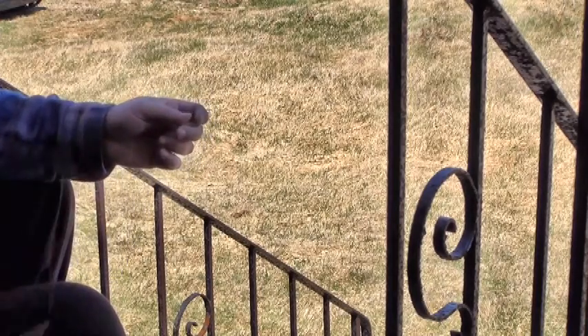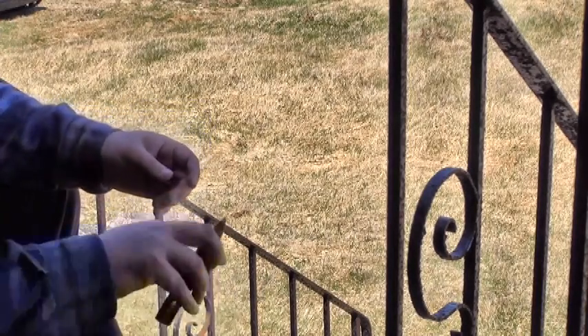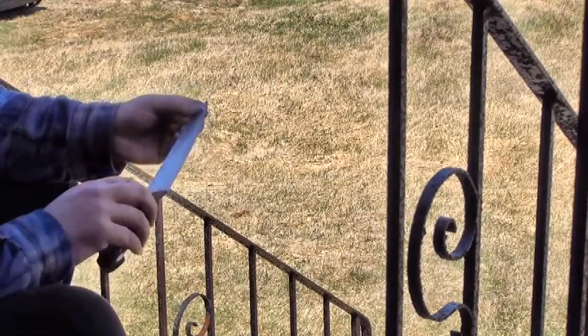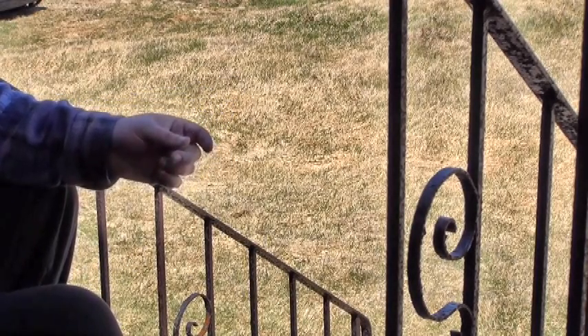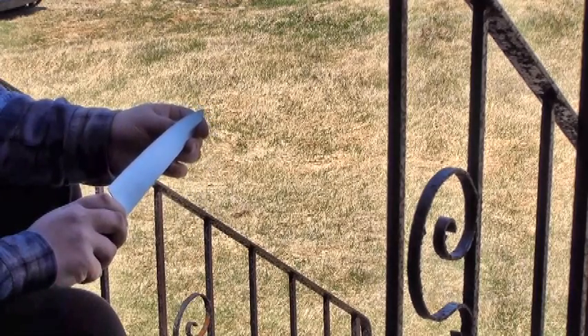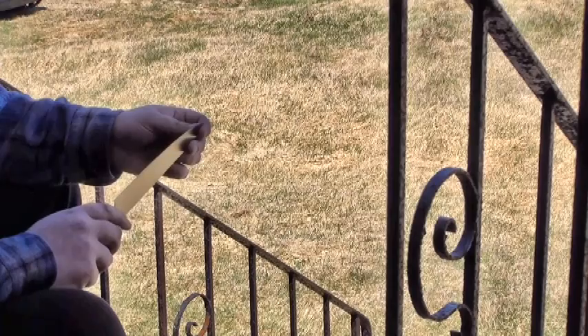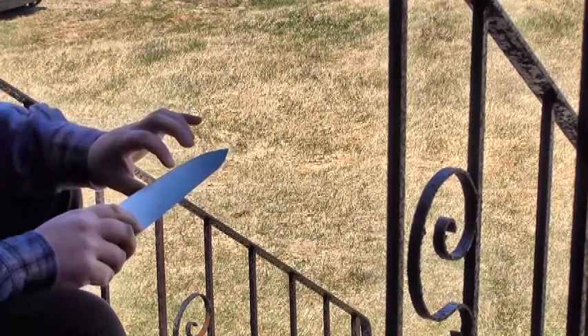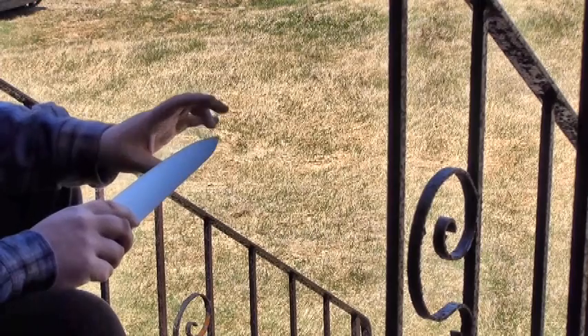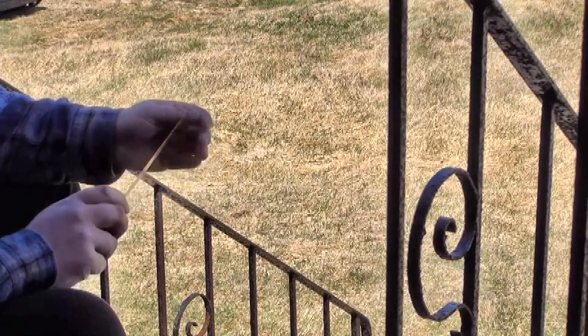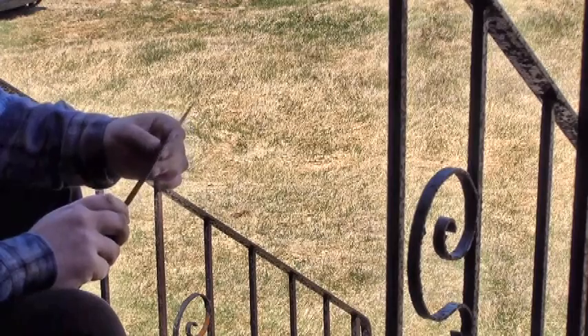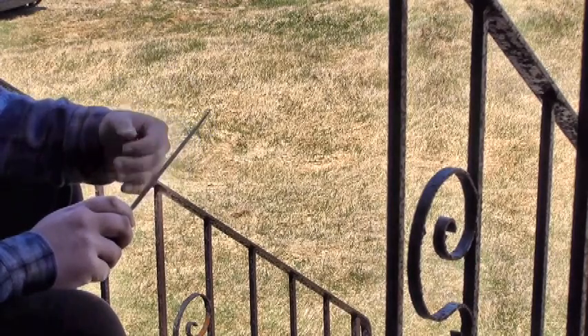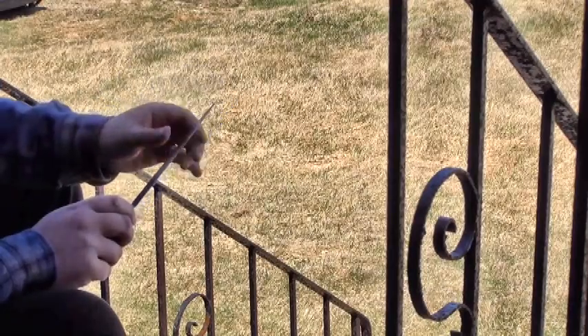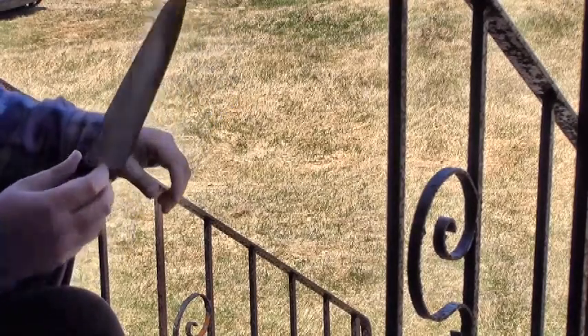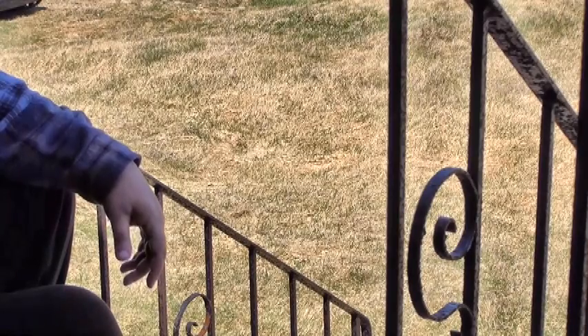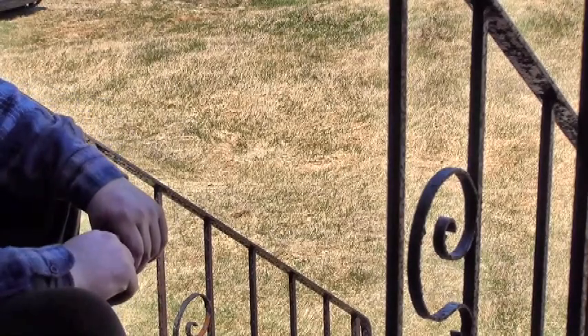Whereas if you gave someone who was used to knives like this, and this is a 420 J2 blade, and all of a sudden you tried to jump them all the way up to this, which is an M390 blade, they would likely walk away thinking that the newer steels are relatively junk, because this steel is tremendously difficult to grind, and you do not want to try to do it on lesser quality stones. You want higher quality stones which have very sharp abrasives, which can cut much faster, and you also want a bit more skill and experience in picking the right grit of the stones, because even small mistakes are not very forgiving when you have such low grindability.